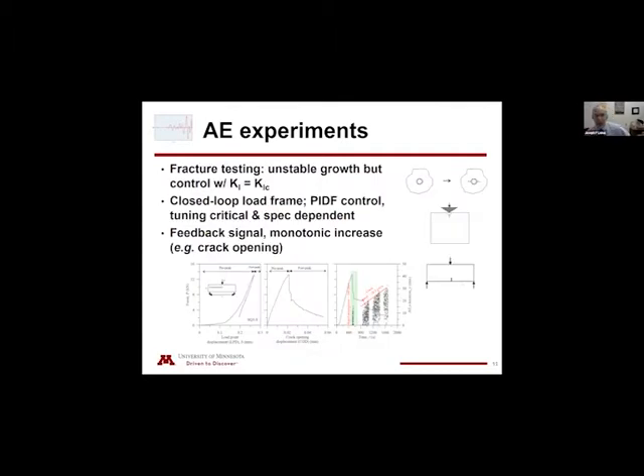So our results for AE are going to be associated with fracture. I'll be showing results from fracture tests on a beam in bending, which is our specimen of choice. Of course, we've also looked at other geometries. Because this beam is a positive geometry, once the crack initiates, crack growth is unstable, in the sense that the force must decrease as the crack propagates. So to achieve a controlled type of crack growth, we typically look at crack speeds that are not very large, on the order of 20, 30 microns per second.